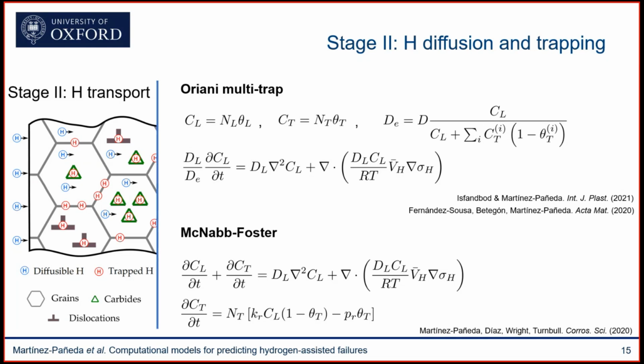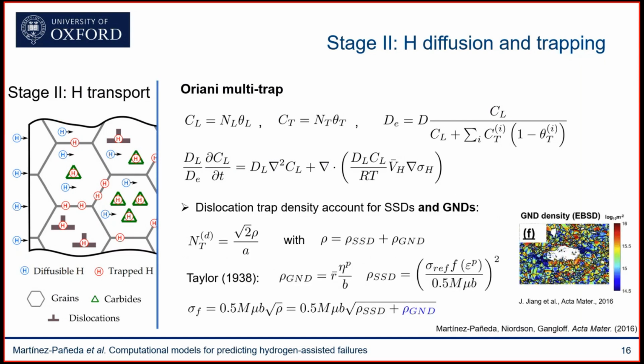And one aspect that I really want to emphasize here is that if you really want to predict what your hydrogen distribution is within your microstructure and you want to consider multiple types of traps, first you need these multi-trap models because you need to be able to quantify the binding energy and the trap density for each of these defects. So you can have hydrogen trapped in grain boundaries and carbides. But also when you're dealing with dislocations, you need to take into account the role that geometrically necessary dislocations play on this.